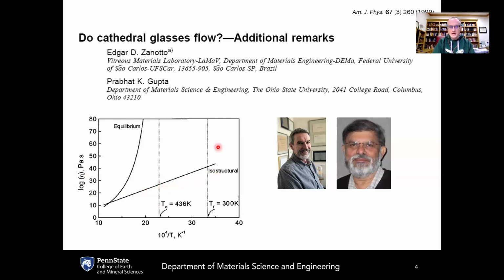And so together, Professors Zanotto and Gupta wrote another paper to follow up from Professor Zanotto's previous paper. This was also published in the American Journal of Physics. This was in 1999. Do cathedral glasses flow? Additional remarks. And they used data from a modern soda-lime silicate glass. This is like a modern window glass. Because that's where most of the data have been published for isostructural viscosity, which is a lot more difficult to measure compared to equilibrium viscosity.